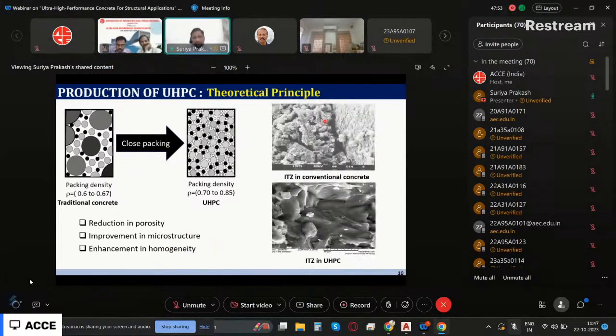So this is a microscopic image, and what I told you about is the interfacial transition zone, ITZ. This is an aggregate, and this is a cementitious system. Between the cement paste and aggregate, you see a lot of voids. This gray color that you see at the interface is the voids. But you don't see such a thing in UHPC. There are no voids at all at the interface. This is a weak link, where the crack will originate when you load the concrete. But if I remove this weak link, then the mechanical performance of the concrete is going to be much better.